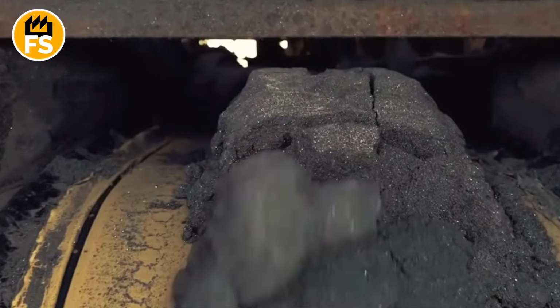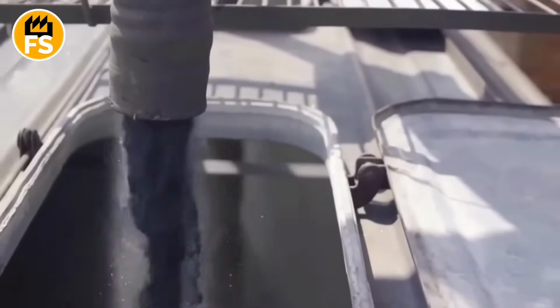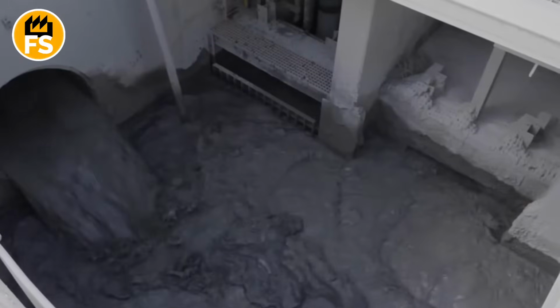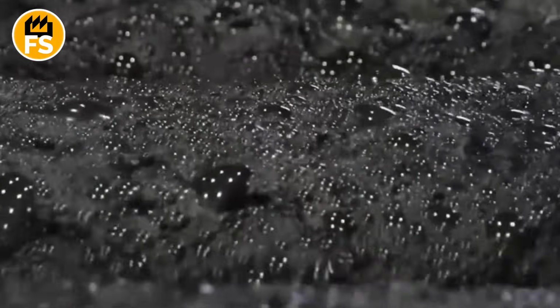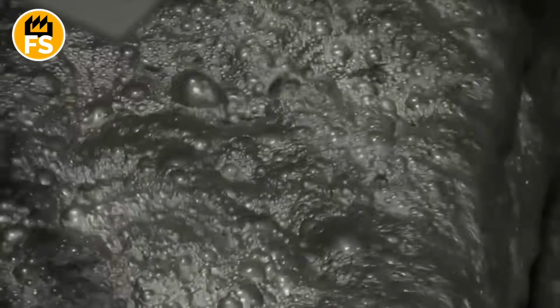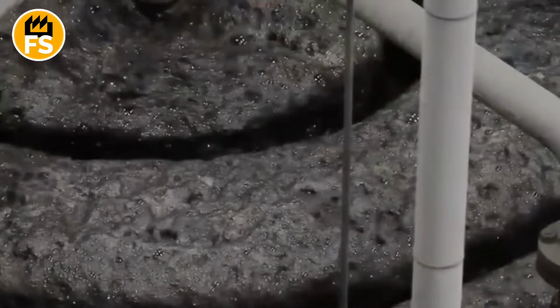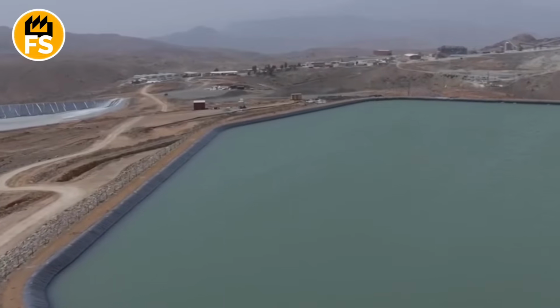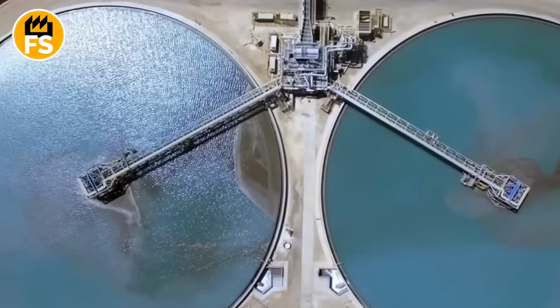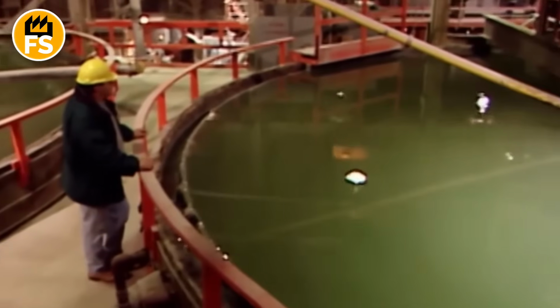Their share in the rock is only a few percent, so after extraction, the ore is crushed and sent to processing plants, where a complex chemical story begins. First, the ore is ground to dust, then subjected to flotation, a process where particles suspended in water are separated using reagents. Rare earth particles stick to air bubbles, rise to the top, while the rest settles to the bottom. This is just the first step, because the concentrate still contains plenty of impurities: iron, calcium, fluorine. Next comes chemical extraction, which transforms the concentrate into high-purity oxides. This is an extremely complex process.